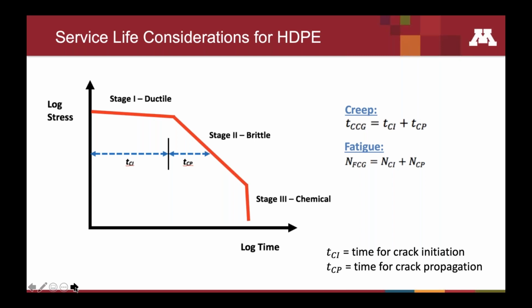The stage 3 failures are chemical in nature, and those are generally just prevented by adding enough antioxidant or ultraviolet protection to the pipe to prevent UV degradation or oxidation of the pipes. And that's a pretty well understood mechanism that the industry has understood for a long time, and we're aware of how to ensure stage 3 failures do not occur. So the main thrust of our research was this stage 2. How can we make sure that that stage 2 failure curve is pushed out to the right far enough to ensure 100-year service life?